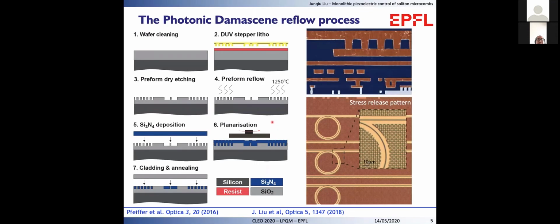To fabricate silicon nitride photonic integrated circuits, we developed and optimized the Photonic Damascene process over the past few years. In this process, we use a clean wafer substrate and perform deep UV stepper lithography on the wafer. And then we transfer the pattern from the photoresist mask to the substrate. We further anneal the substrate to smooth out the sidewall roughness. And then we deposit silicon nitride on top of the patterned preform. A planarization is needed to remove the excess silicon nitride. And in the end, we put on top cladding, anneal, and then separate the chips.